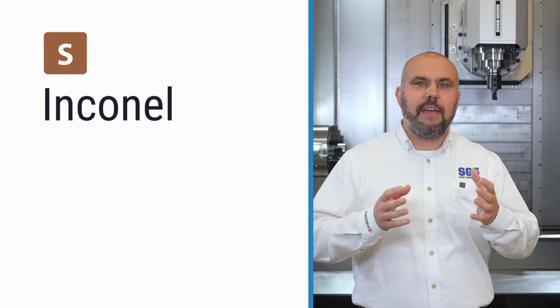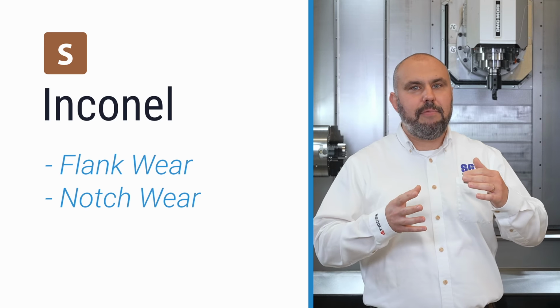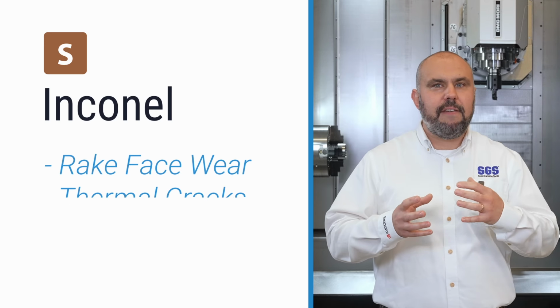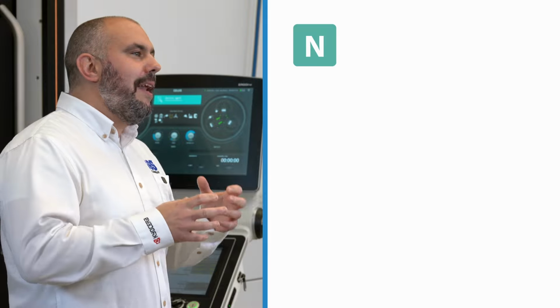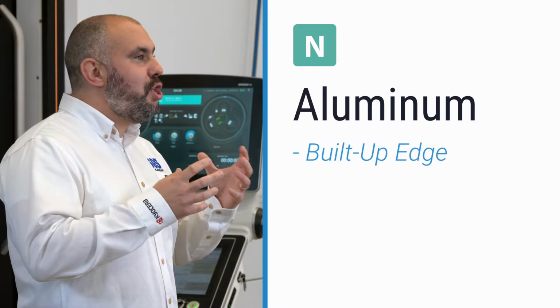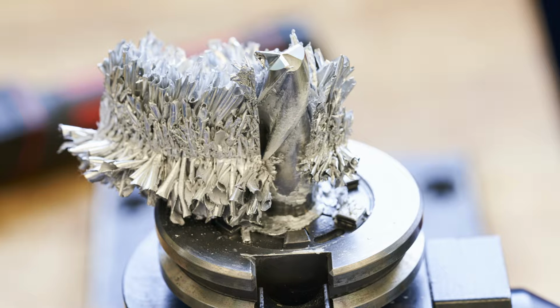Let's talk about wear and analyze it. In Inconel, you're looking for flank wear and notch wear at the depth of cut line, crater wear on the rake face, or thermal cracks. If you hear a pitch change or start seeing the surface finish go downhill, those are early warning signs that your tool is wearing. In aluminum, it's all about built-up edge, chip welding, and flute packing. If you see material stuck to the tool, or if the edge goes dull quickly, there's the geometry telling you that it's overloaded or misapplied.